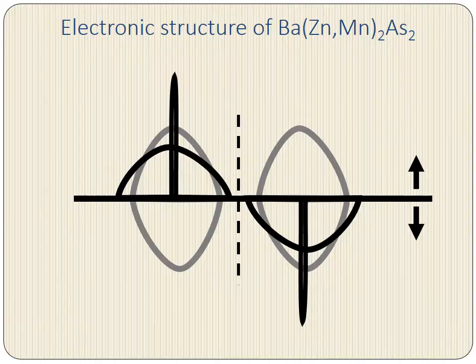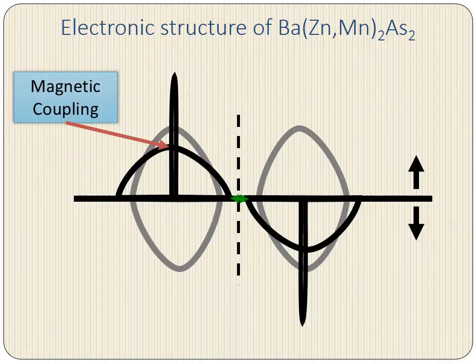Upon hybridization, we see a general broadening of the arsenic band, and we see that the higher energy states are pushed upwards and the lower energy states are pushed downwards. The same can also be observed for the unoccupied barium band. This reduces the size of the gap and lowers the overall spin flip energy. We also found that with increasing manganese doping, this overall distortion becomes more pronounced and eventually the gap will close, which is something that should be verifiable in experiment. In addition, the hybridization of manganese with these itinerant states gives rise to the magnetic coupling, which mediates the effective manganese-manganese interaction in this material.